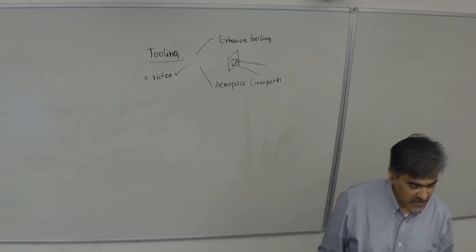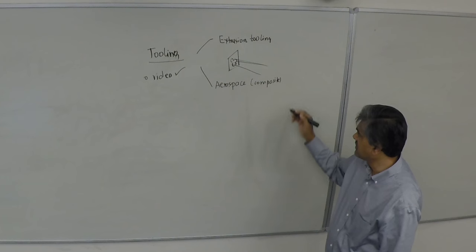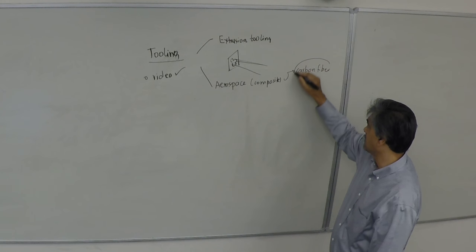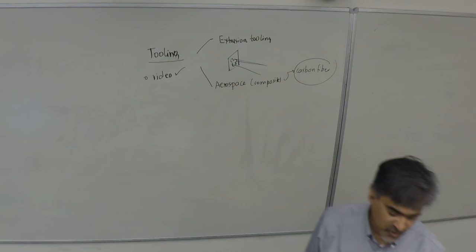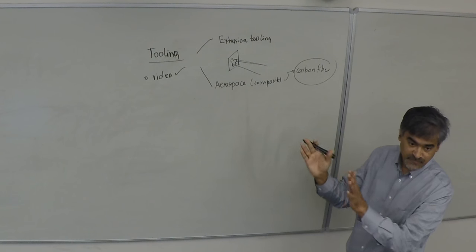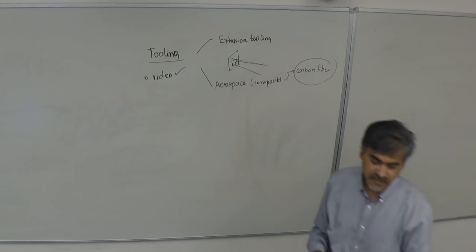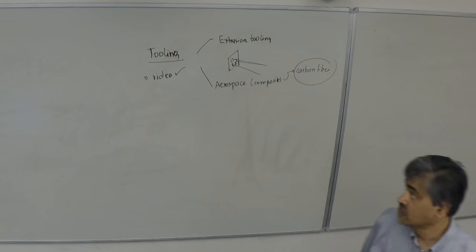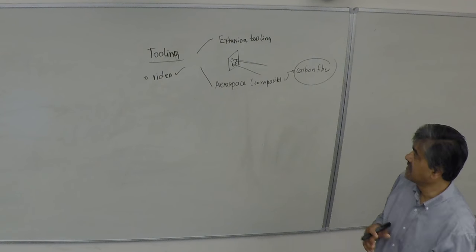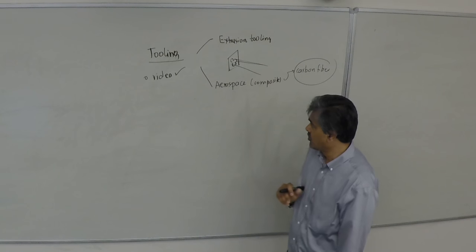We also need to talk about tooling for aerospace parts. You use a lot of composite tools because aerospace parts are very large, awkward shaped, and not stamped in half a second. They are unique parts — low volume but high degree of complexity. The tooling costs in metal can be prohibitively expensive, so in this case you have carbon fiber tools. There is usually a tooling fabric — a heavy tow fabric — used to produce these complex tools, which go into the autoclave. The whole tool is wheeled in after the part is laid down, then wheeled out and detached. You use release film between the part and the tool, otherwise the tool will get permanently attached.